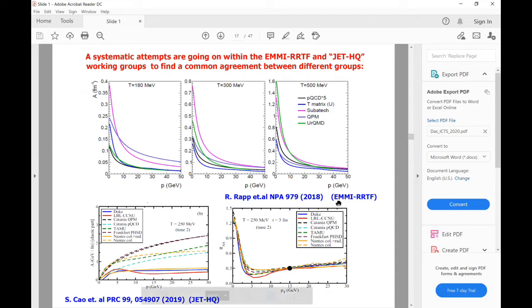The first one is the EMMI Rapid Reaction Task Force. This really brings some of the theory groups as well as experimentalists together to try to understand the heavy quark transport coefficient and to extract the possible heavy quark transport coefficients. As we can see in this model, there are five different cases. They compare the heavy quark transport coefficient, the drag coefficient. So as we can see, excluding the PQCD, in all other four cases, they are able to explain the experimental data within the error bar. But still, there is a huge uncertainty, more than a factor of 2 or 2.5.